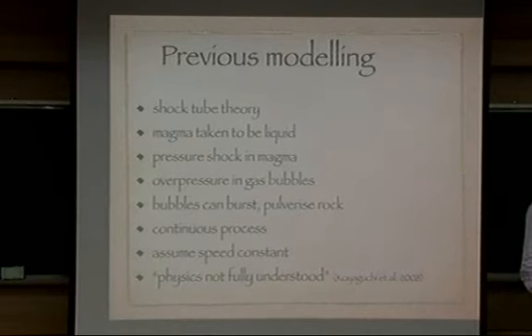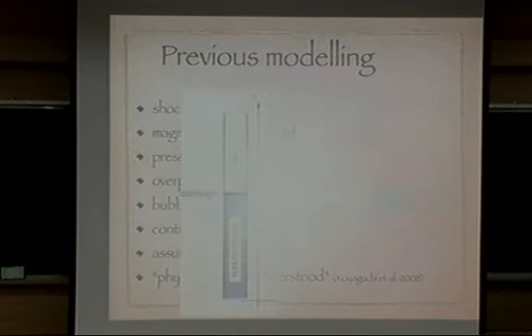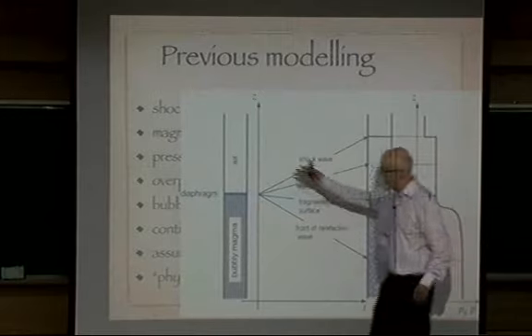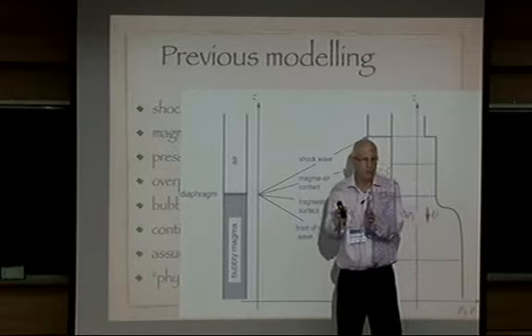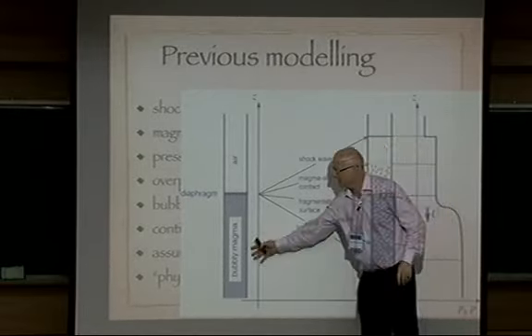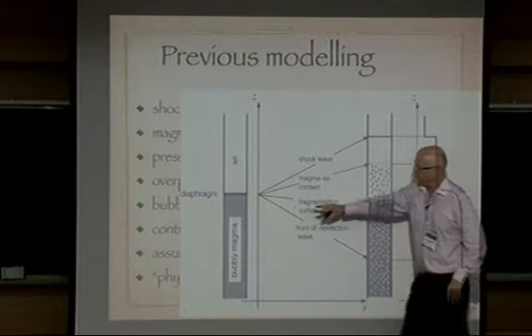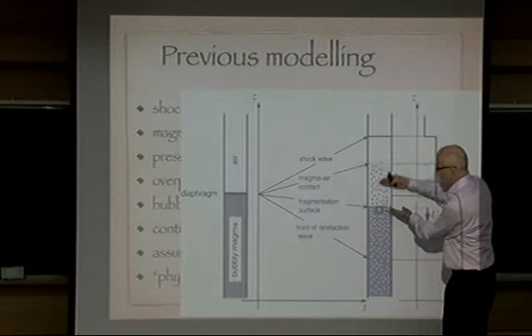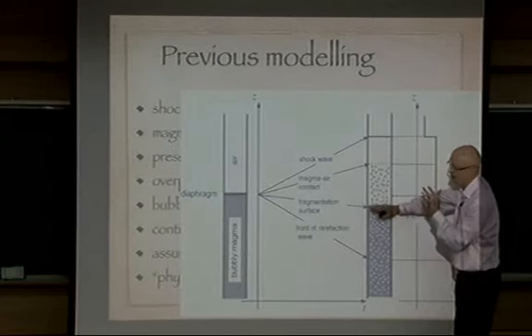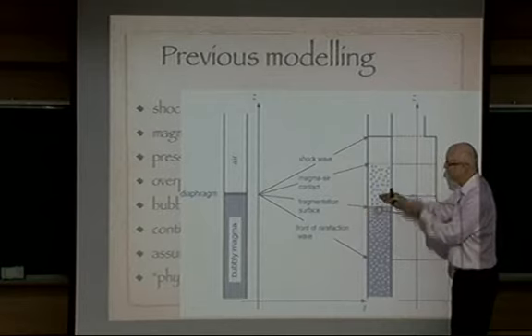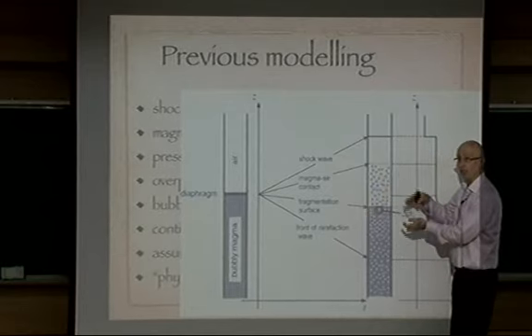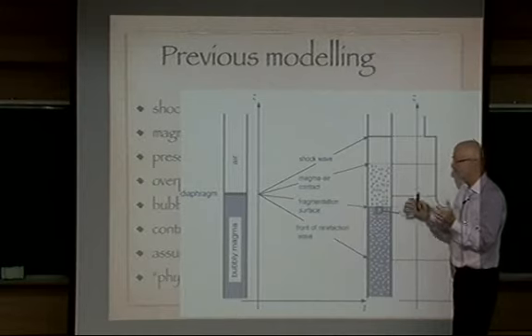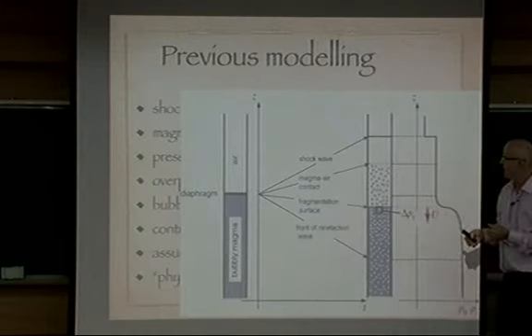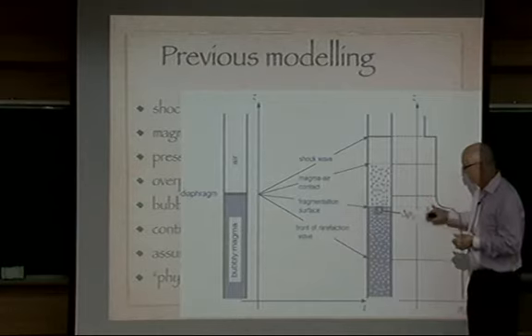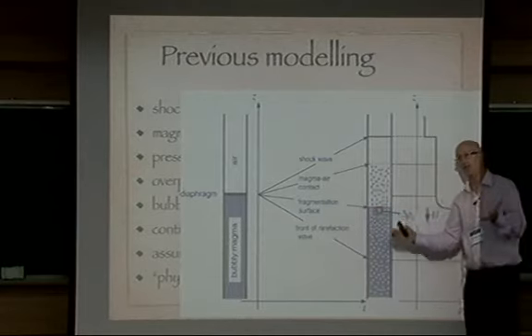But it actually does surprisingly well. This modelling does very well in terms of matching. Here's the model. You've got air and you've got a bubbly magma. They're thinking of it being more like a liquid. Maybe that's right somewhere else on the spectrum, but not so much for these lab experiments. Drop the pressure by popping the diaphragm, and then a propagating shock, actually a rarefaction wave, goes into the magma, with conservation of mass and momentum across the jump, that's all. So it's a nice and simple model, and it has its attractions because of its simplicity. Then they assume the velocity going down is constant, and then they can solve.